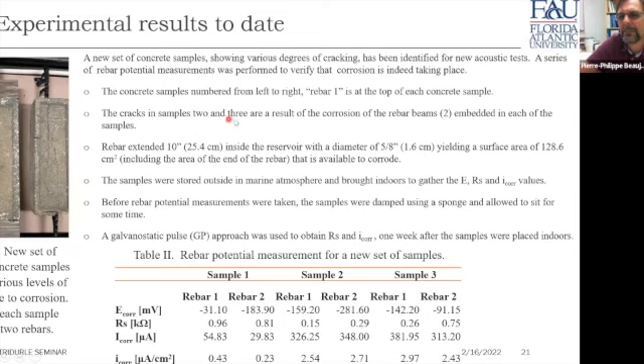Now, the cracks in sample 2 and 3, center and right, are the result of the corrosion of the rebar beams embedded in each of the samples. Note that the rebar extends approximately 25.4 centimeters inside the reservoir, and each rebar has a diameter of 1.6 centimeters, yielding a surface area of approximately 128 centimeters square, including the area at the end of the rebar that is available to corrode. Now, the samples are actually stored outside in the marine atmosphere and literally next to salt water,